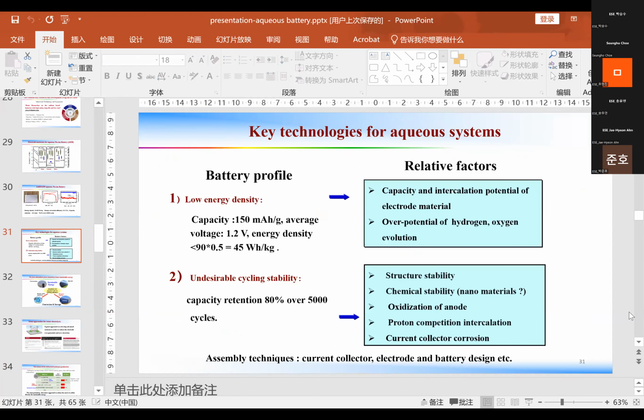So for the aqueous systems, we already commercialized one, but the cycling stability and the specific energy are still limited. For example, there is still the drawback of low energy density in aqueous systems. I think it cannot go over 45 or 50 watt-hours, and on cycling stability we should at least exceed 5,000 cycles. There is also a current collector corrosion problem, and for the electrolyte we still have much work to do on electrode and battery design.